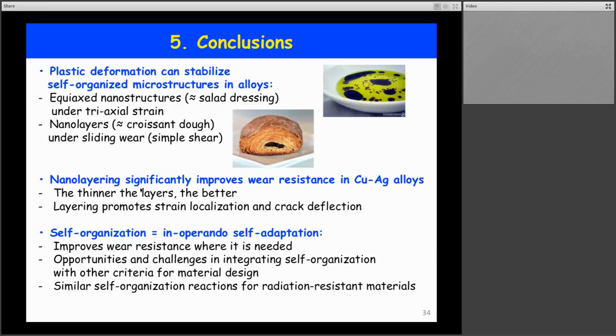And so most seriously, what we found is that this nanolayering significantly improves the wear resistance, that the thinner the layer, the better, probably by promoting strain localization and crack deflection. The broader point in conclusion is that self-organization provides an adaptation for these materials in operando, that is in service. It improves wear resistance where it's needed. And it is interesting and challenging to design materials and integrate this with other criteria used for material design. We might ask, how can we design a material that would be good for wear resistance and for corrosion resistance?